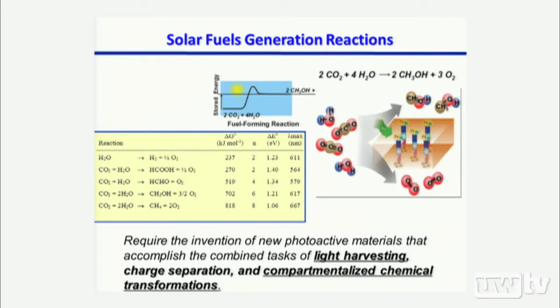Now, just look at a couple of these reactions, whether we are looking at solar water splitting to generate hydrogen, so you split water into hydrogen and oxygen, or a more challenging direction, where you start with CO2 and water and give you all of these different CO2 reduction products, depending on whether you are doing the 2-electron, 4-electron, or 6-electron reduction. So if you look at this whole process, immediately you realize none of these reactions would be happening spontaneously. So you need energy input. That's the solar energy. And then you need basically a catalyst.